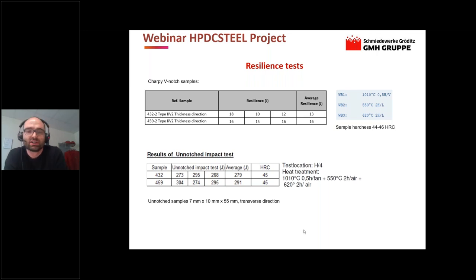We can see the single Charpy V notch samples on the top of the slide, but also the unnotched impact sample tests on the bottom of the slide. The unnotched samples, with the averages but also the single values, fulfill the demands for sophisticated applications. We also show the laboratory heat treatment of these samples, which were put through a simulated heat treatment. And it has to be said that the quenching was performed on moving air. This has to be recognized.